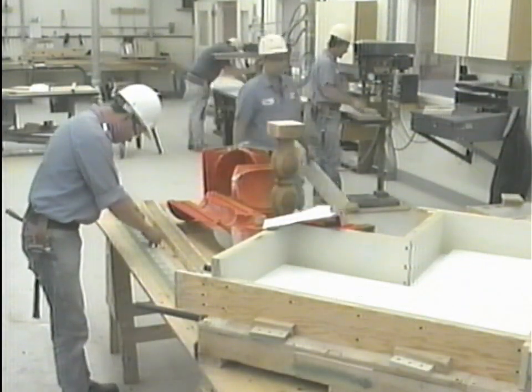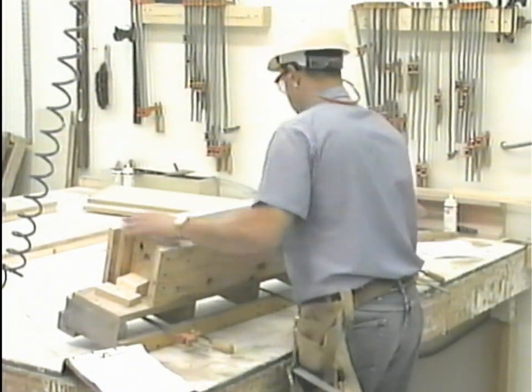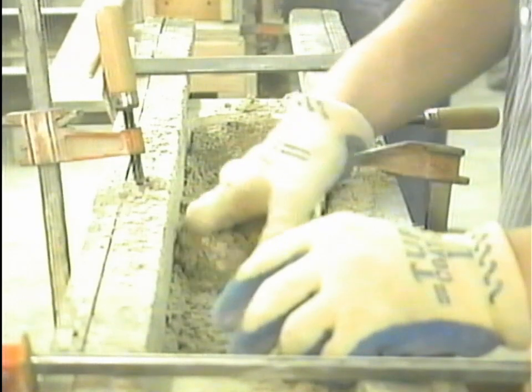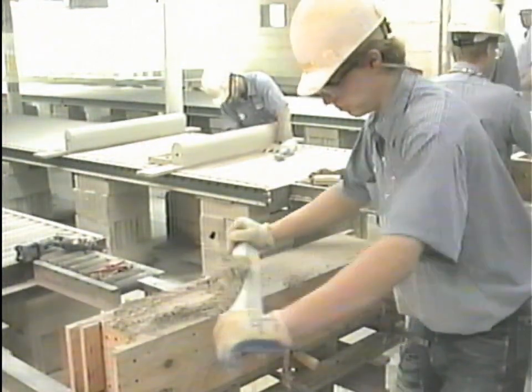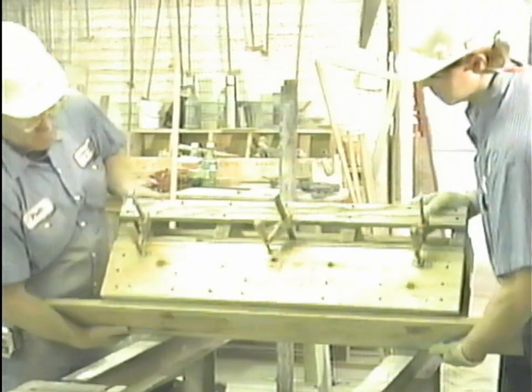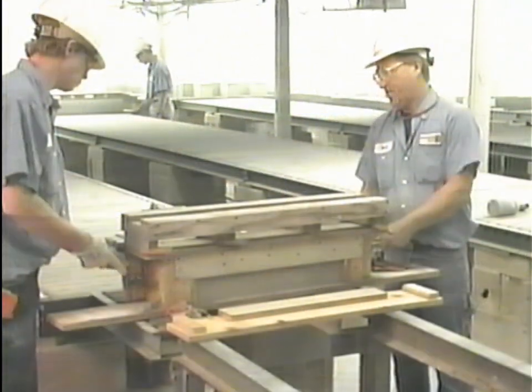Molds are typically built from high-density overlay plywood, fiberglass, or rubber. The mold is then assembled and clamped securely for ease of repetitive use. The ready mold is filled with the moist mixture. Rebar or mesh is also added in the dry cast process. An intense tamping is applied. Next, the mixture is screeded and troweled. A pallet is applied to the flat side to allow the turning of the mold. The cast stone is now reversed to an upright position.